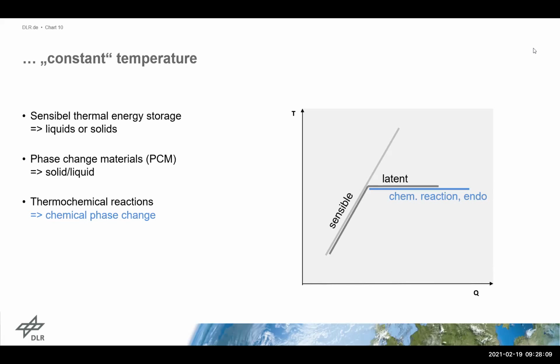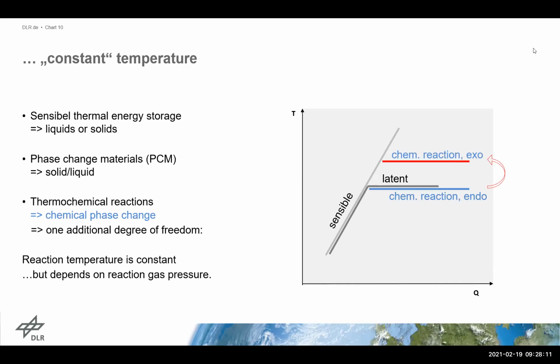This is only half of the truth, because the interesting thing is now, since we have only one straight line, we can of course adjust the reaction or the storage temperature by adjusting the gas pressure, the reaction gas pressure. And thereby we can increase the storage temperature, for instance, for discharging.